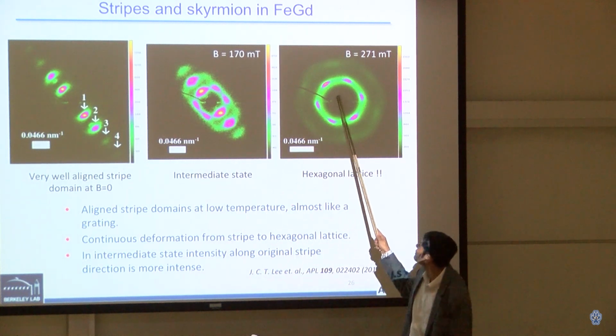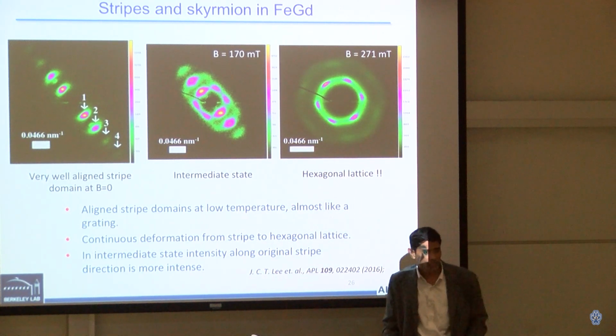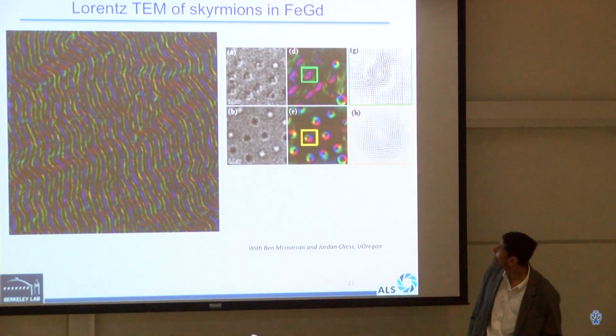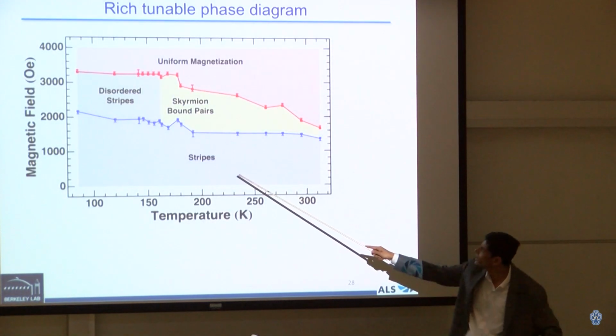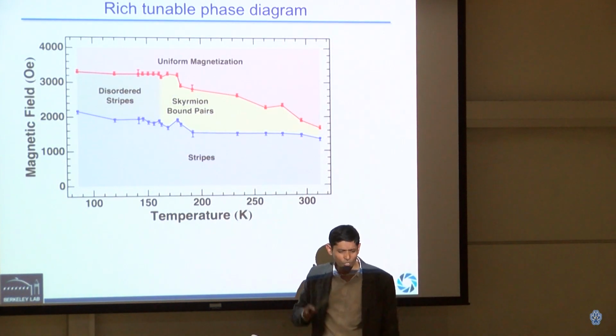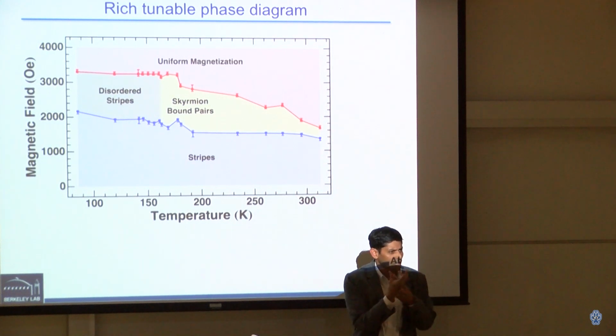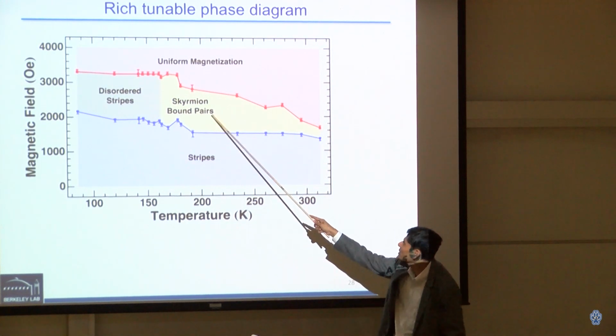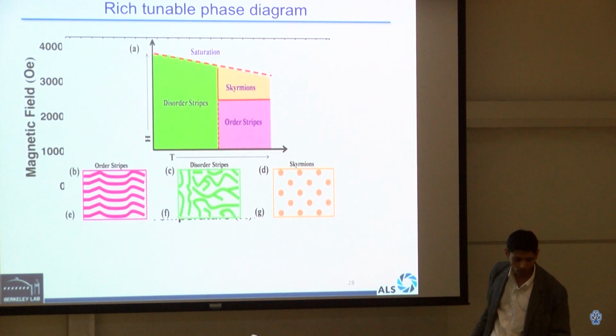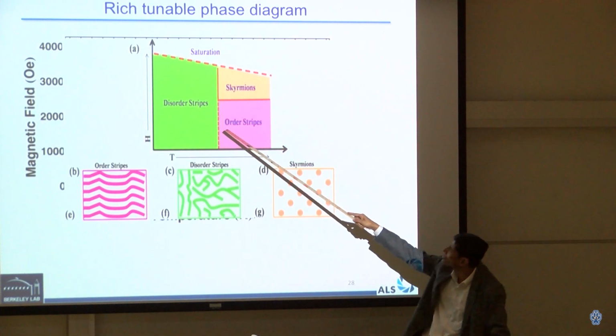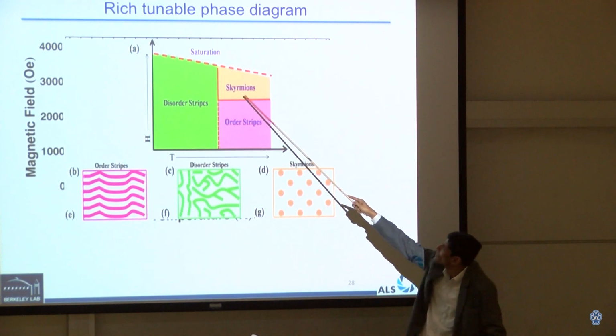And then they are giving rise to a skyrmion. So the question is that when James measured the phase diagram, he found that there are highly aligned stripes. There are a little bit of disordered stripes, like noodle type, labyrinth. And then there are skyrmions and uniform magnetization. So we can now make this kind of schematic: there are disordered stripes, ordered stripes, and skyrmions.